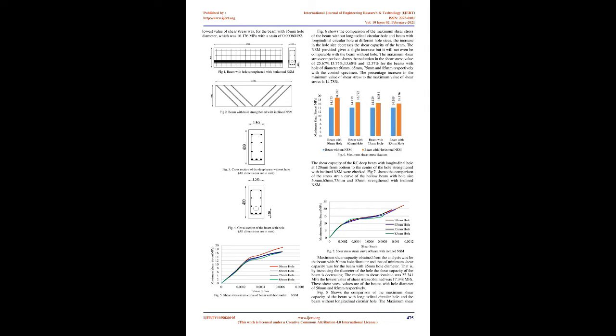Horizontal NSM was provided at the sides of the hole and inclined NSM was provided at the side surface with 45° inclination. By varying the diameter of the hole, the shear capacity and load carrying capacity of the beams were checked. Fig 1 and Fig 2 show the beams with horizontal NSM and inclined NSM. For conducting the finite element analysis, a deep beam with longitudinal hole was chosen. The hole in the beam was positioned below the neutral axis of the beam. The exact position of the hole was that the distance from the bottom of the beam to the center of the hole was 120 mm.